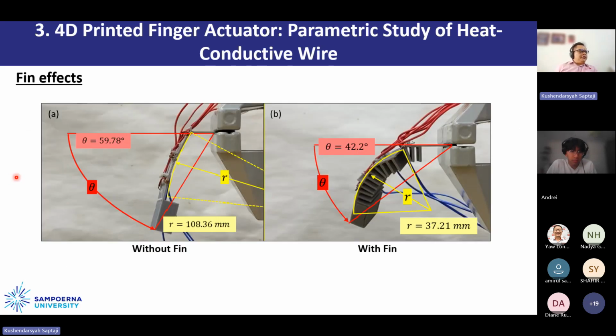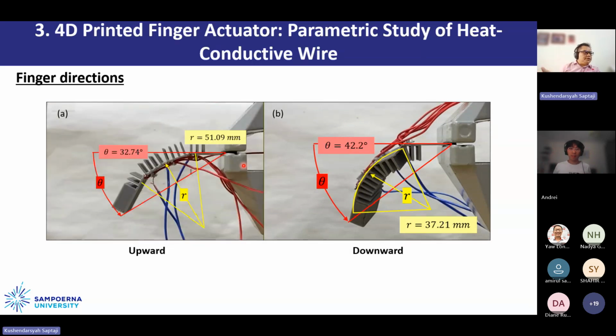Again, we are also curious whether the fin gives an effect or not. We can see that without the fin, the deflection is quite high, but the shape is like bending only at this point, while by having the fin, it helps to create some curve in here. We also tried to change the set, making the fin upward, and we compared it with our downward fin, and you can see also in here the upward fin is not as good as the downward fin in terms of the deflection angle and the radius.